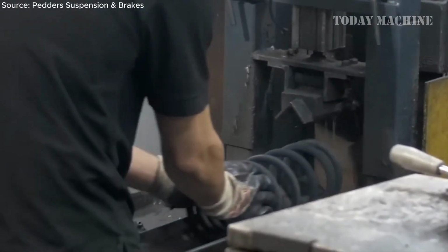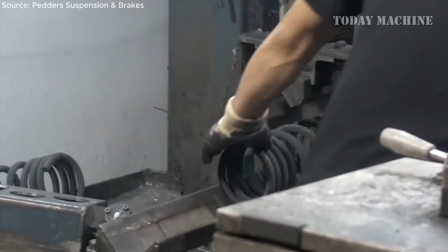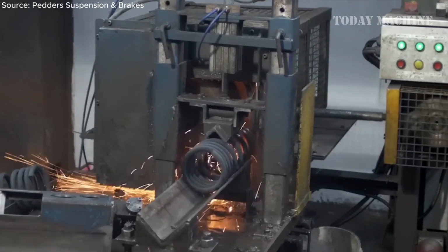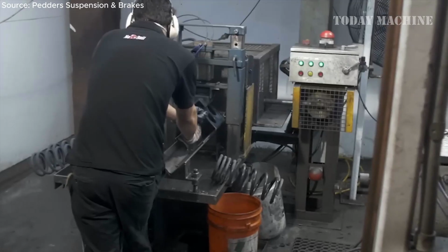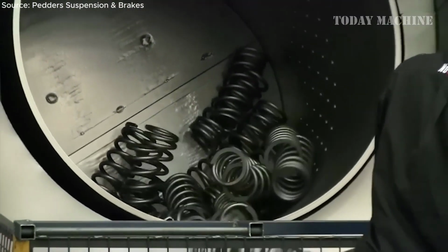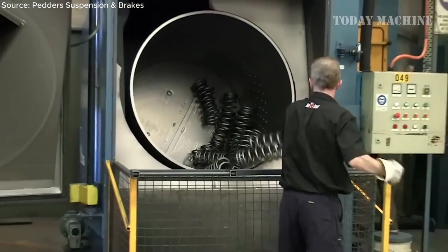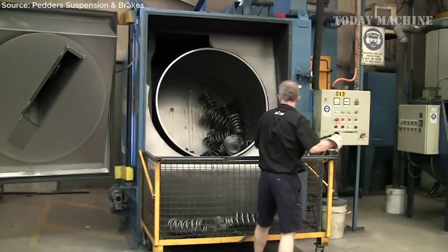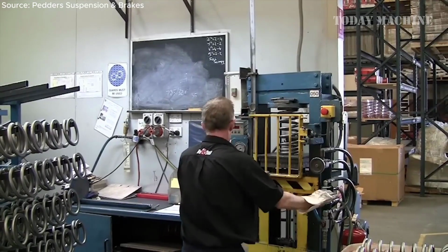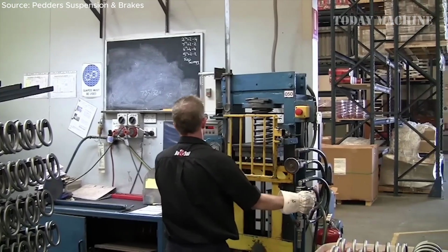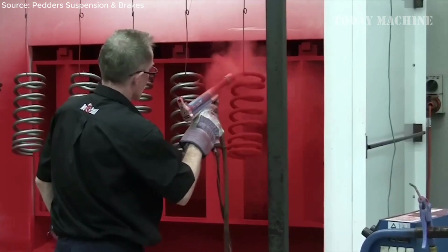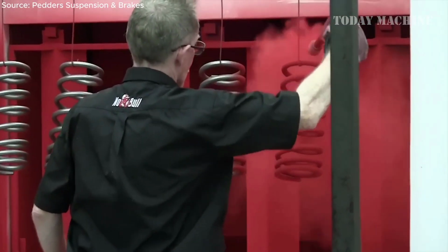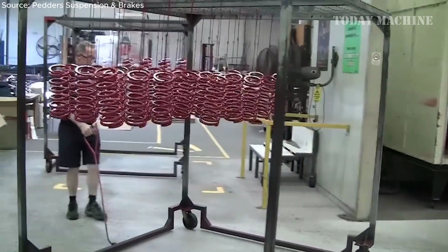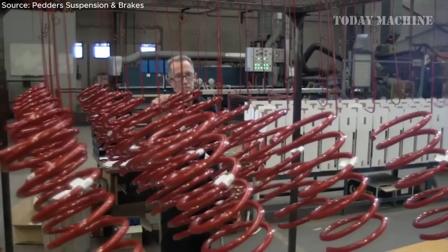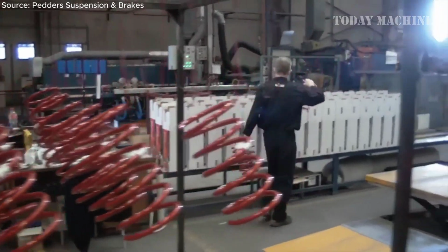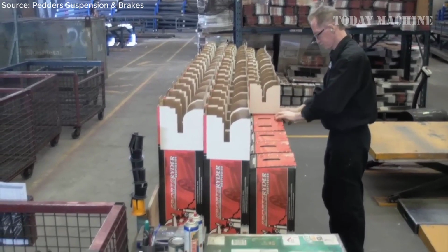Next, the coils are ground for flat ends if required, followed by shot peening, where steel beads remove impurities and relieve stress. Afterward, each spring undergoes rigorous testing, including scragging and load height verification. Once approved, the springs are powder-coated using an electrostatic process and cured at 220 degrees Celsius. Finally, the finished coils are cooled, packed, and prepared for distribution, ensuring high standards and reliability.